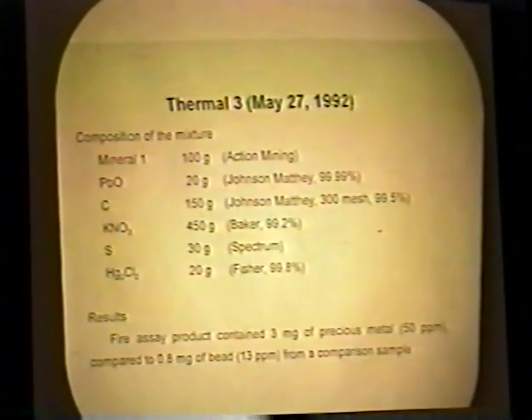We do this 2 times. One is this kind of experiment. Second is a comparison experiment sample, which means without mercury. So for the Thermal 3, we use Thermal 3, produce 3 milligrams of precious metal, which corresponds to 50 ppm, compared to 0.8 bead from the comparison sample, which is without this part.